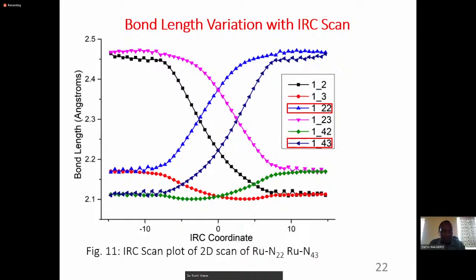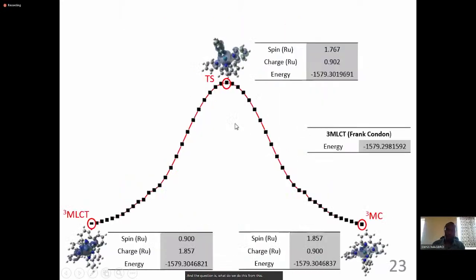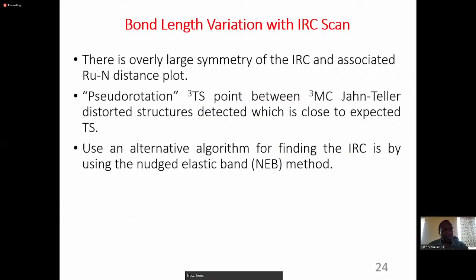So from the analysis of the IRC, with the plot of the bond lengths, zero is the transition state, and on the left and the right are the triplet MLCT and the triplet MC. What you find about this particular plot is that it is really symmetric. And the question is, what do we deduce from this? This is just a plot of the IRC. Now, from the plot here, we see that there's overly large symmetry. You can see that both points are the same.